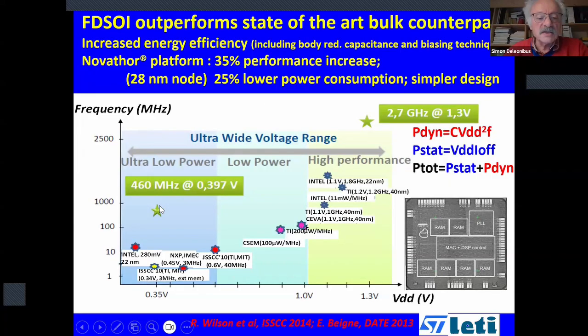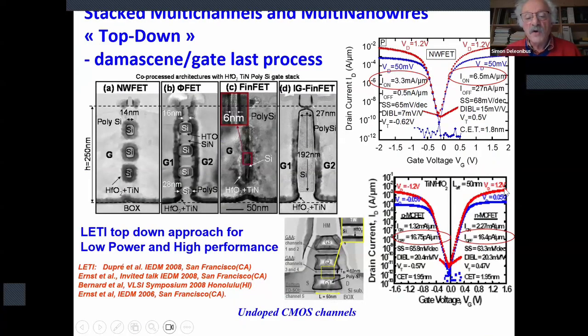Okay, so here you can see that at high supply voltages, you can see that we have tested this technology to extremely low supply voltages. Thanks to the drastically reduced capacitance due to isolation of these films, you can reach much higher performance. So it's very important to keep this in mind to reduce power consumption, because it very strongly depends on the supply voltage. So basically, for a given